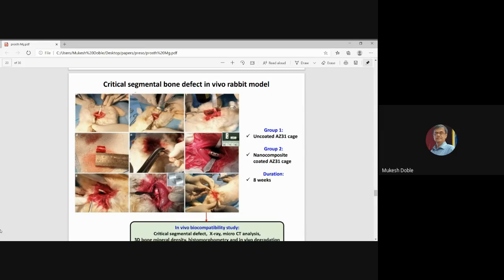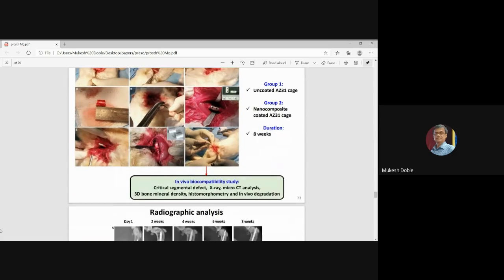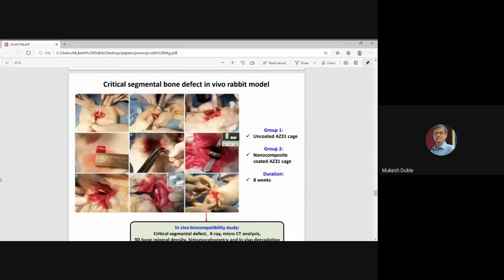So we went to rabbit, and this shows a pictorial. So we had two groups of rabbits. One is uncoated AZ31, that is your aluminum, zinc, magnesium alloy. The other one is polycaprolactone hydroxyapatite coated same alloy. So the experiments were done on rabbit. A defect was created in the bone, and these cages were placed. So this is a typical picture, as you can see here.